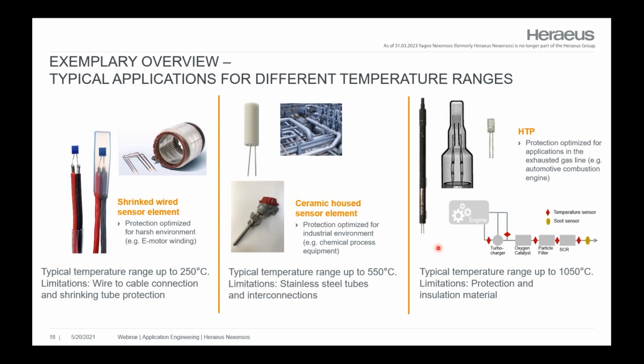Here are some different examples where you see how these temperature steps could be overjumped. On the left side, you see again that application in the E-motor. You have here that shrinked wired sensor element, which has really a good performance in terms of sealing, in terms of vibration and resistance in mechanical topics. But on the other hand, there is a temperature limit, which is limited up to 250 degrees. If you need higher temperatures, for example for chemical process equipment, petrochemical devices and so on, there is typically a different housing necessary. You can't work with these cables which are melting at temperatures over 250. You can't work with that shrinking tube, which is limited up to 250, and so on and so on.